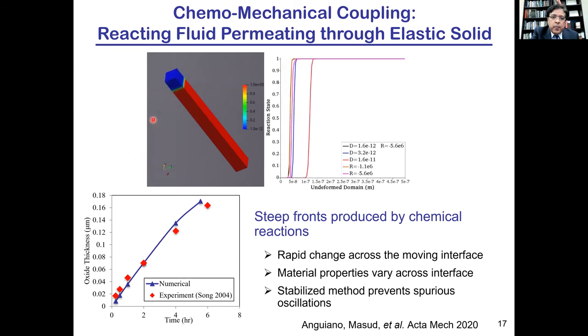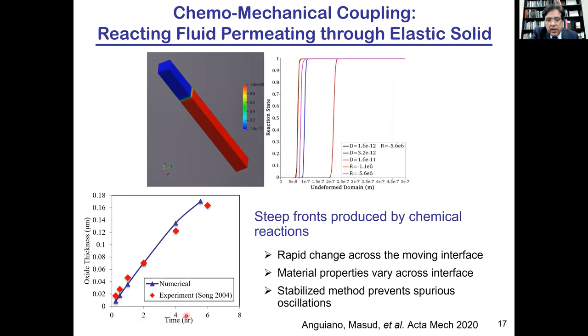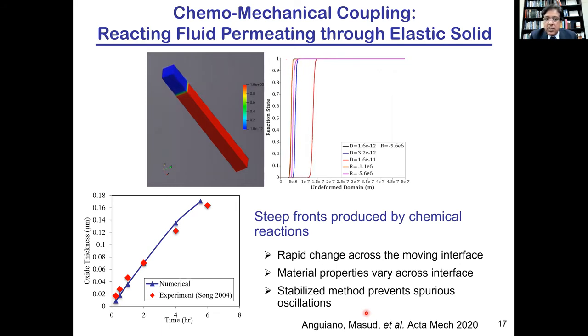This simulation shows the reaction front diffusing into the unreacted material, and the material is transforming rapidly across it. These lines here show the advancing front for different mechanical material properties. It is a very steep front, but we are able to capture it without any overshoot or undershoot. Here is the comparison with the experimental data of oxide thickness as a function of time. So stabilized methods provide us a mechanism to stabilize the moving reaction fronts across which the mechanical properties are varying rapidly, and the geometric deformation is substantially large for this problem.